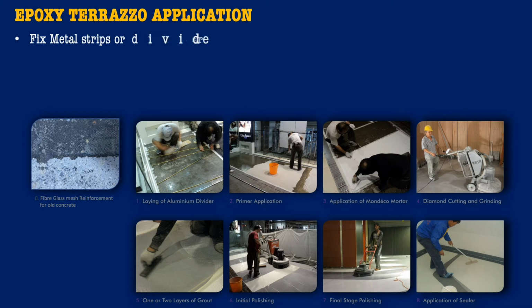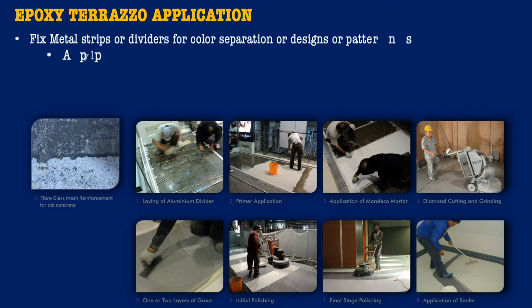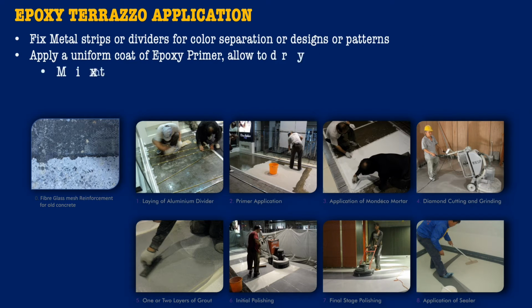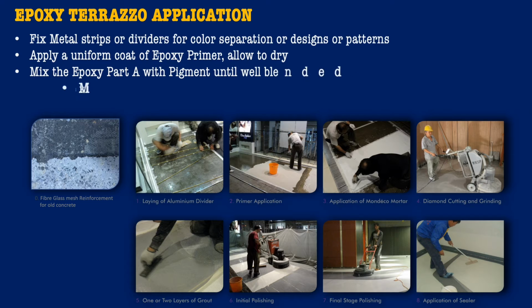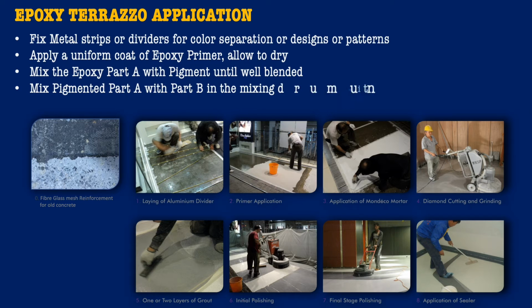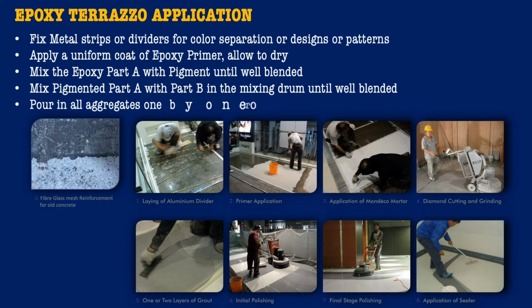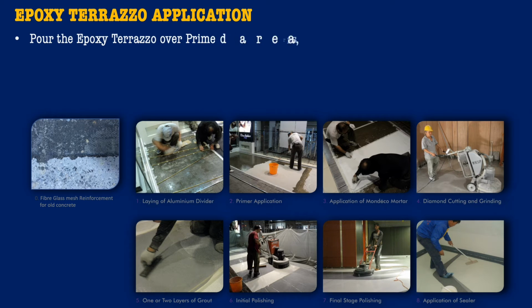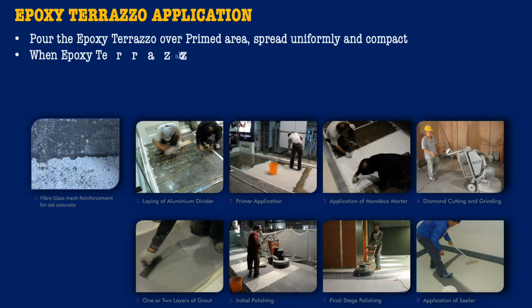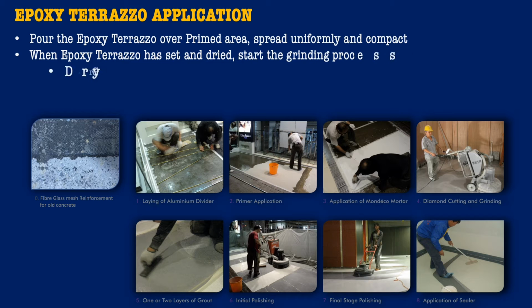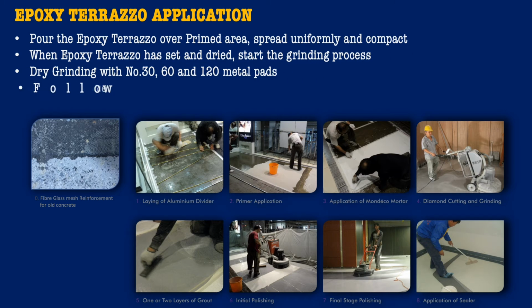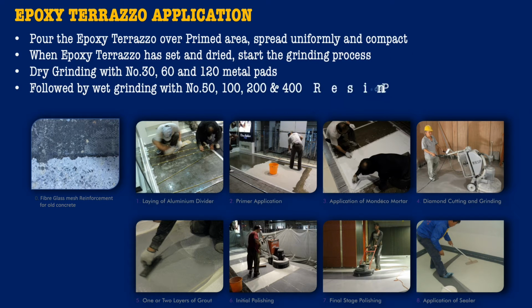Fix metal strips or dividers for color separation or designs or patterns. Apply a uniform coat of epoxy primer, allow to dry. Mix the epoxy part A with pigment, followed by mixing with part B in a mixing drum until well blended. Pour in all aggregates one by one or together, and mix until consistent. Pour the epoxy terrazzo over primed area, spread uniformly and compact. When epoxy terrazzo has set and dried, start the grinding process.